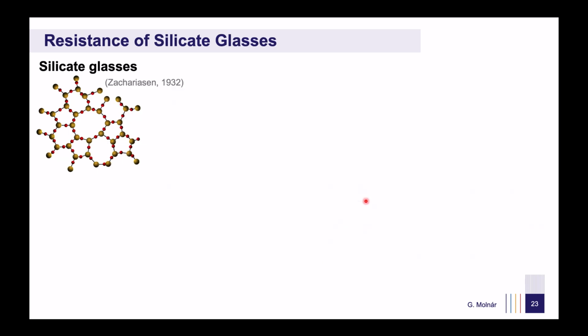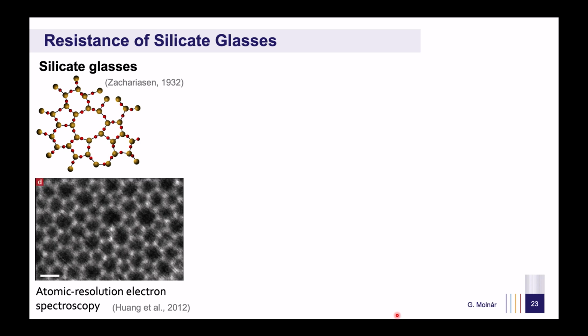We have seen how powerful the phase field model is in capturing various fracture phenomena. Now I would like to shift our focus to an important question: how can we measure different length scales in real materials? We chose glass as our material of interest because it is relatively simple and lacks a macroscopic length scale. Unlike polycrystalline materials, glasses have no grains, grain boundaries or dislocations, making them ideal for modeling at the atomic scale. Silicate glasses consist of randomly distributed atoms forming unique ring structures. This structure was first theorized in the 1930s, but was only recently confirmed using atomic resolution electron spectroscopy.